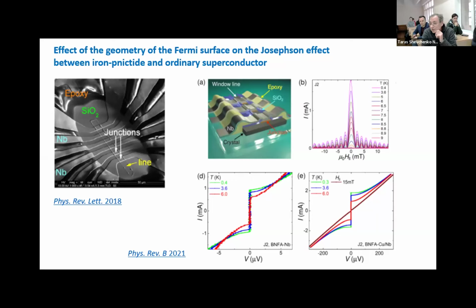But actually here we have found that this complex superconducting order parameter is also a problem, because you have destructive interference between different signs of the order parameter. This characteristic of the current-voltage curve is called ICRN, which defines, let's say, this jump multiplied by this jump: critical current IC and normal resistivity Rn. Their product in a normal superconductor is proportional to the superconducting gap. But in this superconductor, it is highly decreased because of this